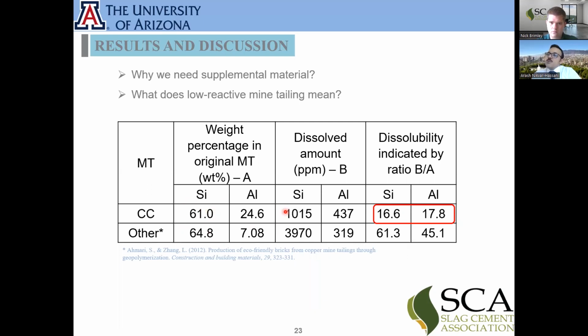And when we checked how much silica and alumina we can get after 24 hours of submerging these powders inside the alkaline activator liquid, and compared it with the active mine tailings in the industry, we saw, wow, there is a big difference. The mine tailing we had, after 24 hours, we were only able to take out 16% of the silica from the material and 17% aluminum. However, compared to the data we have for active mine, if you get the material from an active mine, then you can get 61% of silica and 45% of aluminum.